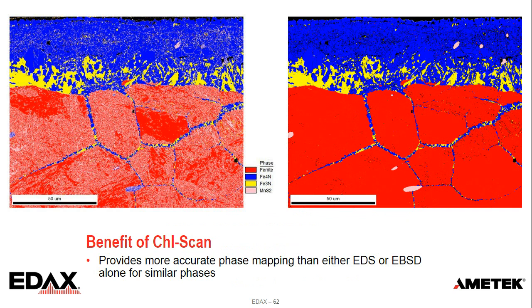I think this just shows very nicely why using both together is very nice. It's a very easy way of better resolving the phase information correctly. We get a better overall picture, and there's really no penalty for having both. And then we can look at the orientation information.